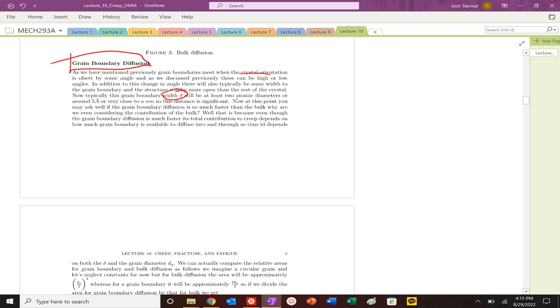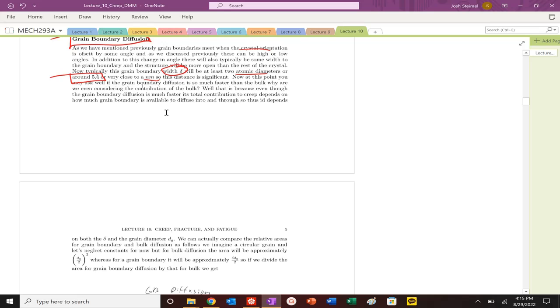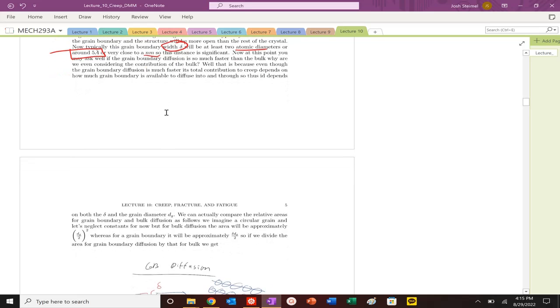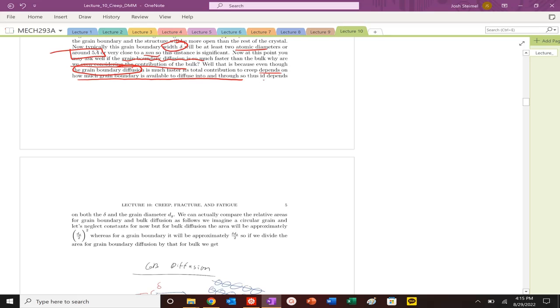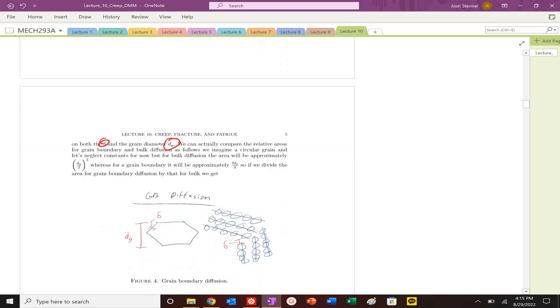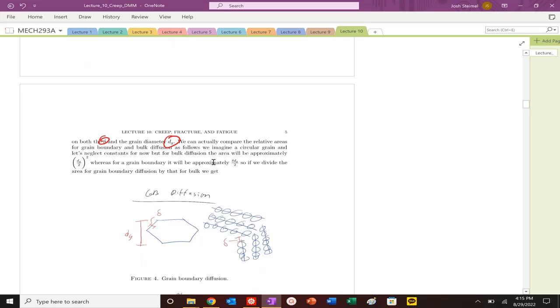Now the question you may ask is, if diffusion is always higher in the grain boundary, why don't we just always diffuse along the grain boundary? Well, there's limited grain boundaries in our material. Typically, your grain boundary width is going to be at least two atomic diameters around five angstroms. You're limited in terms of that space, that spacing there. That grain boundary width is typically constant.